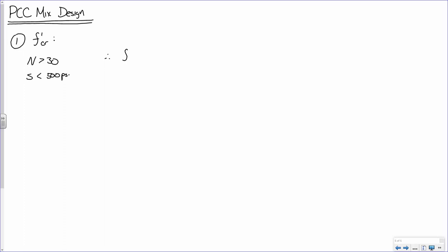Therefore, you tell me, how am I going to compute f'cr? f'c plus 1.34S. Does everybody see that? So f'c plus 1.34 times the standard deviation. That is 4,000 PSI, that's our target, plus 1.34, and what's our standard deviation? 400. So what do we get? 4,536 PSI. Do I have a second on that value? All right, step one's done.